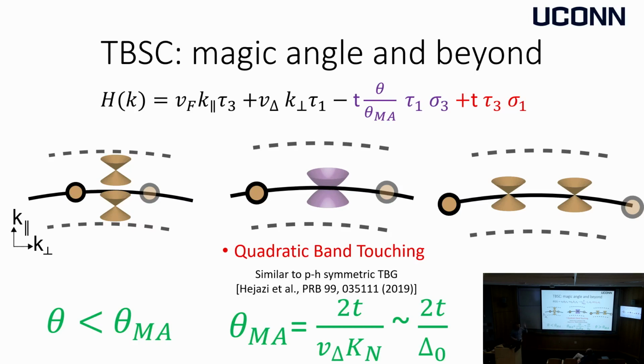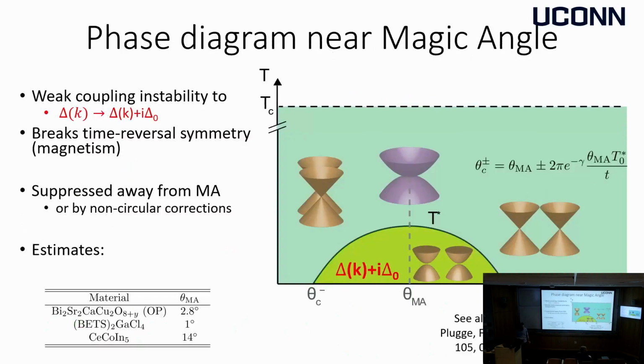What happens here is that you have a quadratic band touching, and the density of states for a quadratic band touching is actually finite, even right at 0 energy. So you have a bunch of density of states, all jumbled in one single momentum point. You would naturally expect this to be unstable. And I'm going to quickly walk you through what the prediction is.